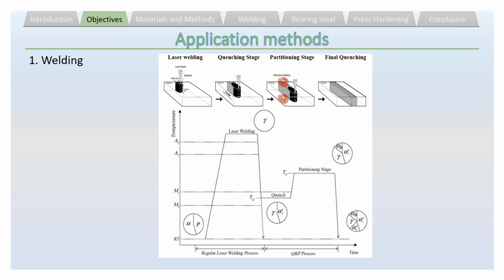If we look at the objectives of our work, we have 3 processes. The first one is welding. In this work, I worked on laser welding. You know that laser welding has a very high concentrated energy, which means that after welding, we will get martensite because of the very high cooling rate. And this martensite is not what we would like. So the idea of this work comes from quenching and partitioning, and what we have done is that we controlled the temperature just after welding at a special quenching temperature between MS and MF.